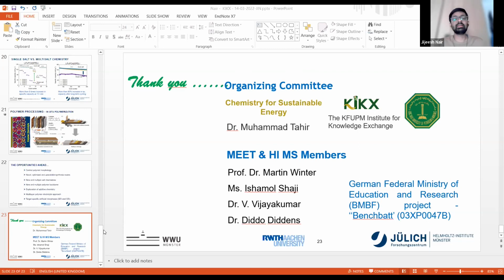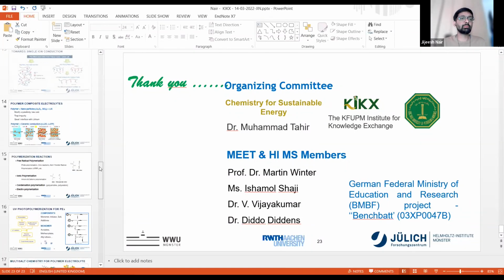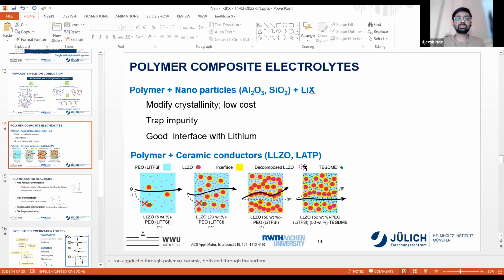As I mentioned, this depends on which kind of polymer composite you want to create. For example, in this slide, you can see that even if you add 5% of ceramic electrolyte, it is not going to conduct because the activation energy for that conduction is higher. And if the surrounding area has a lower activation energy for ionic conduction, it will conduct through that part. So you have to really balance the concentration, and decide which part of your composite you want to conduct. That is the first point. The second point is the size. When you reduce the size of the particles, there is an issue with the grain boundary.